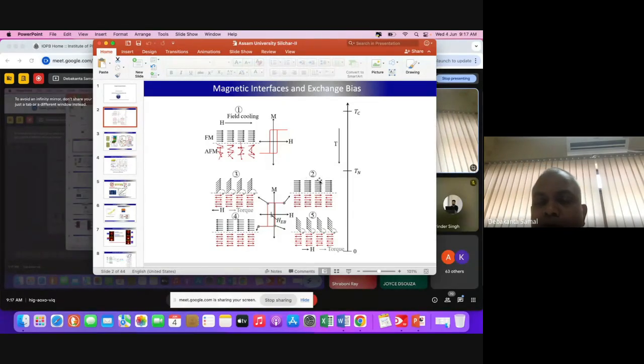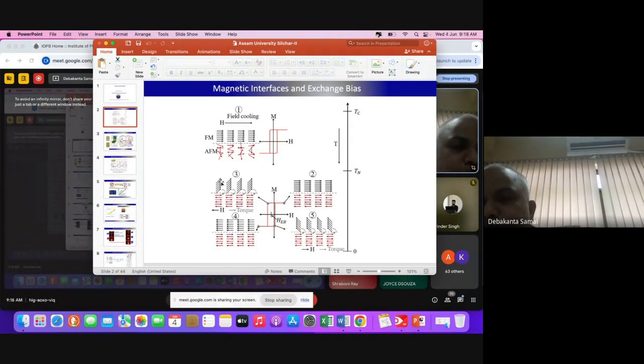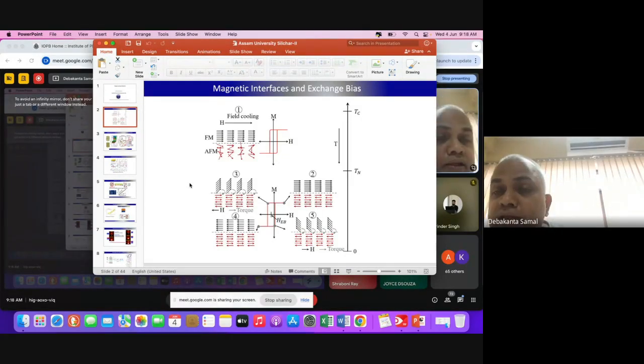Now when you are retracing the field in the negative direction, look at 3: these ferromagnetic spins try to follow the field direction because they want to rotate along the field. You are going from the first quadrant to the second quadrant, changing the field, so the ferromagnetic moments want to follow the field. But at the interface, there is strong coupling with the antiferromagnet. The antiferromagnetic spins do not allow the ferromagnetic spins to freely go back into the field direction. So you require more field in this kind of system.